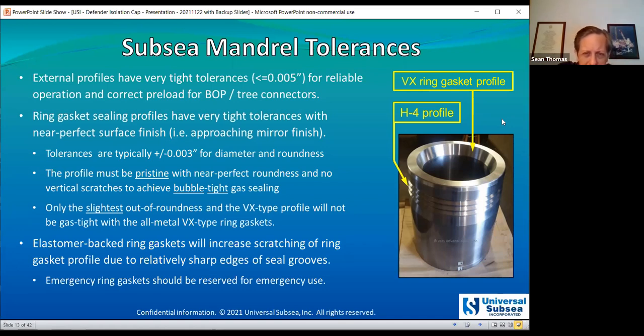Any scratches, any tolerance problems, particularly if the ring gasket profile is out of round, even a little bit, that will typically cause significant problems with gas tight sealing. So in some cases, the operators will use a ring gasket with elastomer inserts, but we caution about use of those because the seal grooves on those ring gaskets can actually increase the scratching of the ring gasket profile. They're okay to use once basically, but you generally don't want to use an emergency gasket repeatedly over the course of the well. You really want to reserve those for emergency use rather than routine use.